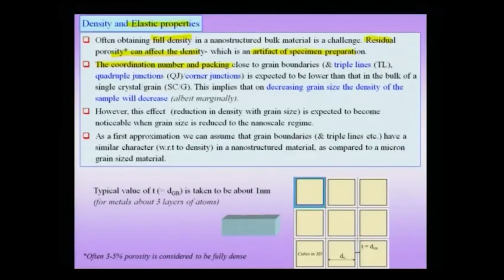The coordination number and packing close to the grain boundaries, and which also includes triple lines, which I short form call TL, and quadruple junctions, the QJs, which sometimes in literature are also called corner junctions, is expected to be lower than the bulk, or if you compare it to the single crystal. This implies that on decreasing the grain size, the density of the sample will decrease. Though this is expected to be a marginal effect, not a drastic one, nevertheless, when you decrease the grain size, in other words, you increase the amount of grain boundaries and triple lines per unit volume, then you expect that the density would actually decrease for a polycrystalline nanostructured material.